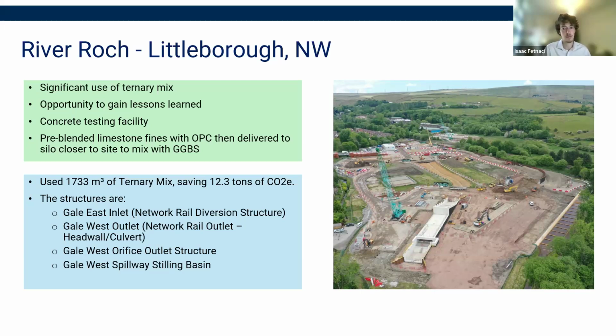What they did was they pre-blended limestone fines with OPC, and then they delivered to a silo closer to the site to mix with the GGBS. So you've got your ternary mix there with OPC, limestone fines, and GGBS. And it was a great chance for a large-scale trial of ternary mix and to gain experience using it and lessons learned. And also a case study was produced about this to spread awareness and knowledge of this concrete mix. So next slide, please.